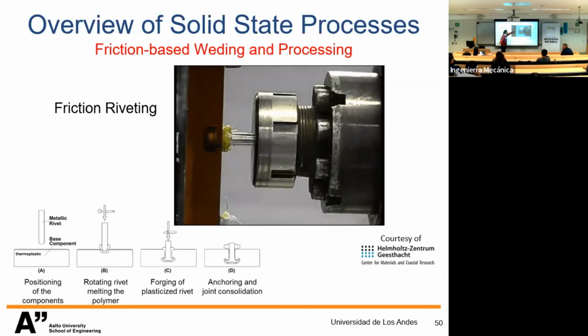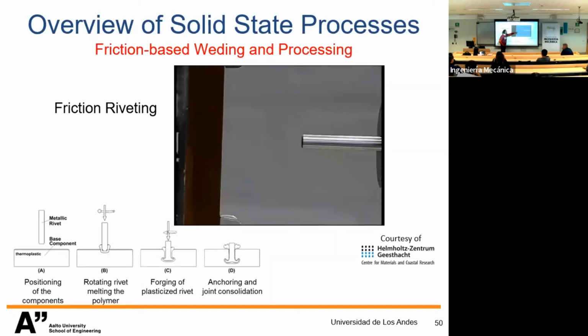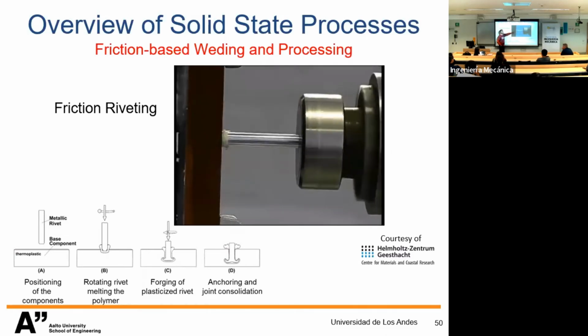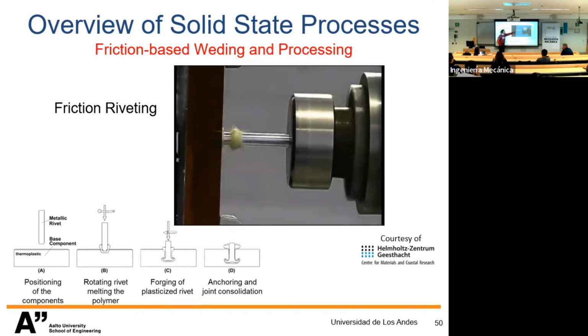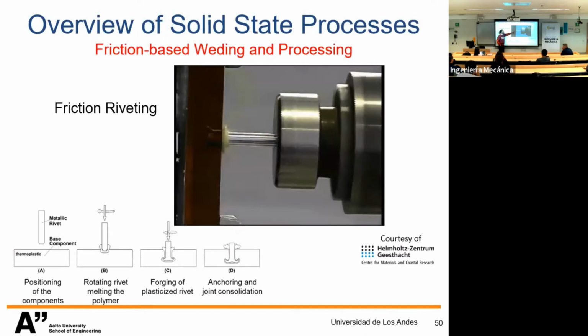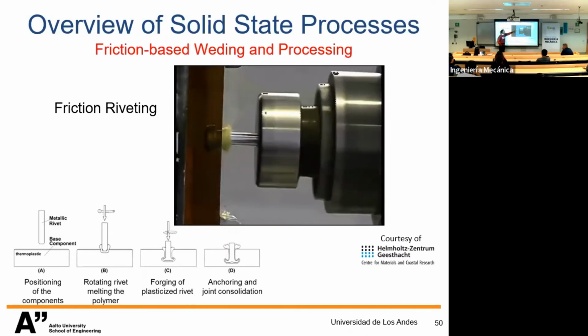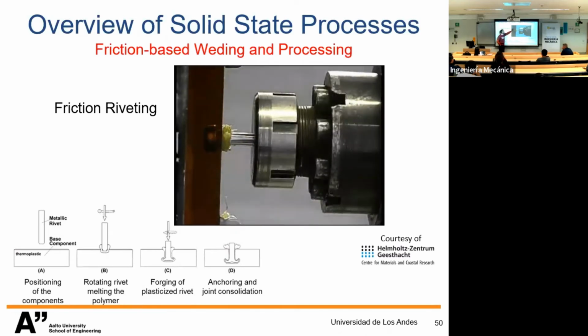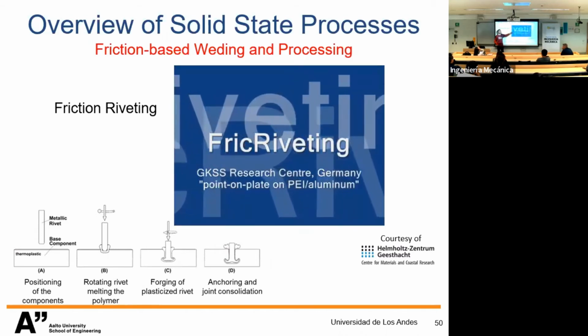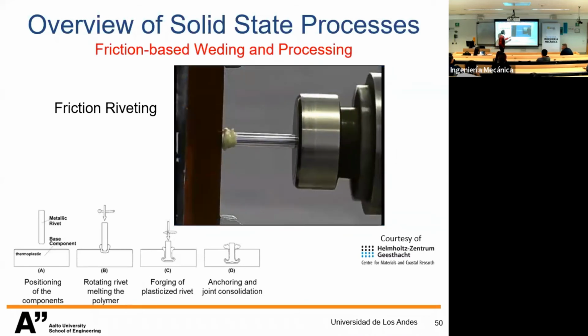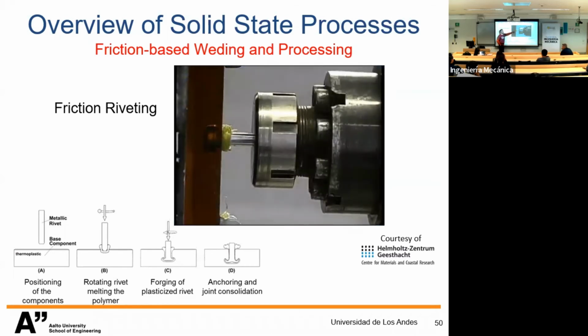So you see the deformation of the metal when it is inserted in the polymer. This is harder than the polymer, so it penetrates. Okay, but at some point, the deformation is localized in the metallic material. That strength comes down and it starts to deform inside of the polymer, creating this clinching effect, a mechanical joint. Okay. So why is it harder and then it gets softer?